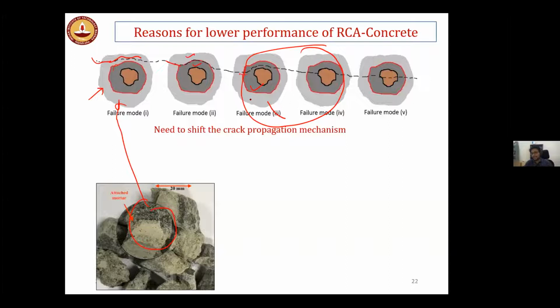So this is the main reason why the strength improvement techniques are not able to work in the case of recycled concrete aggregate. This shows that we need to shift the crack propagation. What we want is either the crack should go through the aggregate, because the aggregate strength is around 100 MPa, or the crack should go through the new mortar, because the new mortar, as engineers, we can optimize, right? We can make it 50 MPa, we can make it 60 MPa. So what we want is either failure mode 5 or failure mode 1.